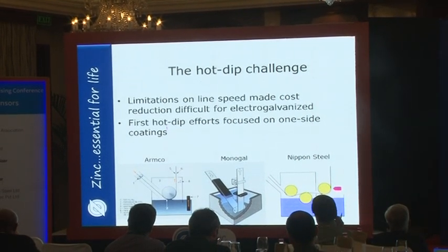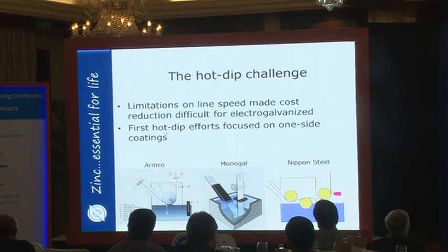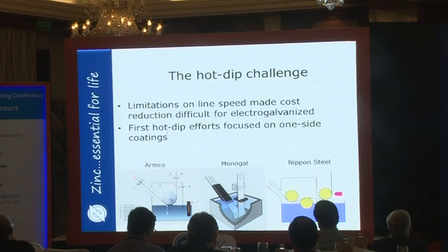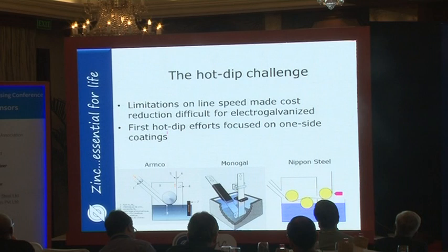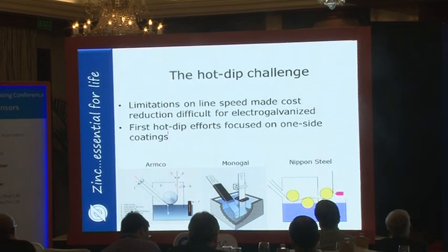To allow for the exposed quality back then, we really didn't know that much about how to do this. Armco had a one-side coating, Usinor in the middle had its monogal coating, and Nippon Steel had sort of a coil coating arrangement where they were in the galvanizing line doing a one-sided coating. So these were rather difficult processes to use, but they served the purpose for a while with hot dip while we developed our knowledge about the hot dip galvanizing for exposed.